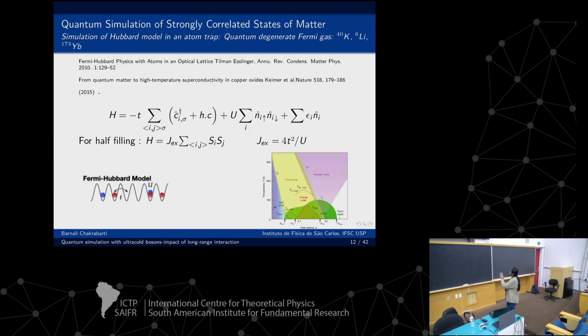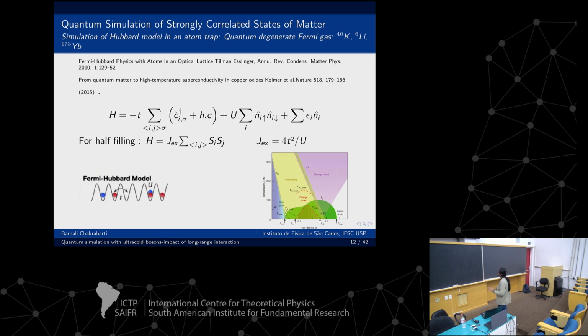You can see that this is a zoo of phases, which means you can find many different phases. I would like to point out a few things. On the x-axis there is the doping. When there is no doping in this cuprate material, there is the expected antiferromagnetic order. But when the doping starts, there is d-wave superconductivity, which means some anisotropy is observed. And there is also a kind of pseudogap. We do not know the actual interpretation of this gap, or what unusual phenomenon in this cuprate material causes it. That is a puzzling question for physicists.